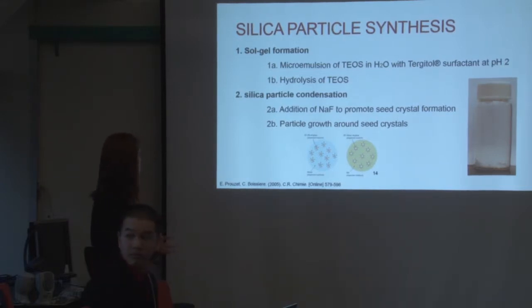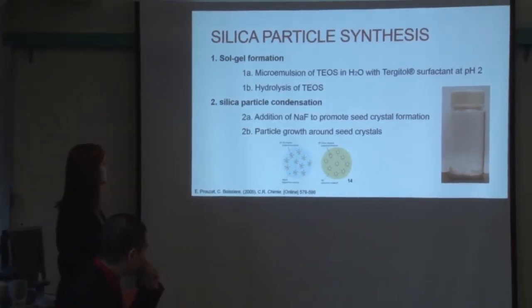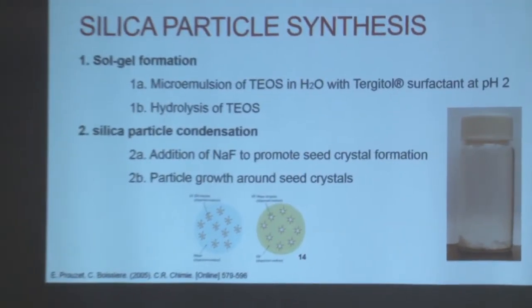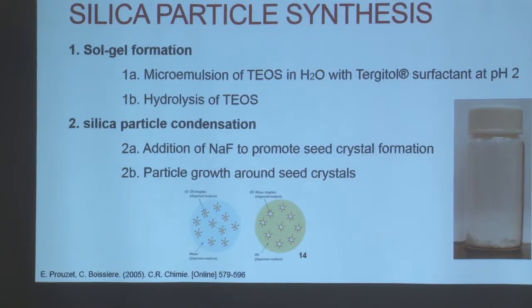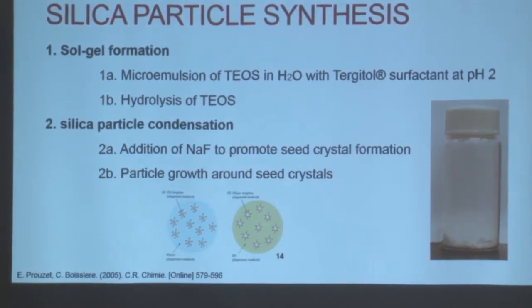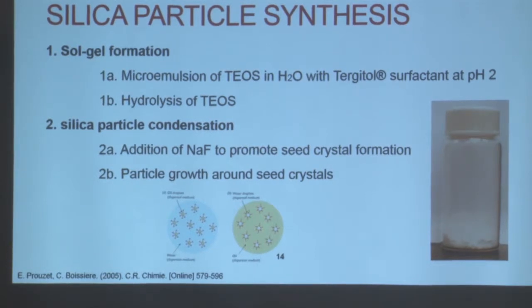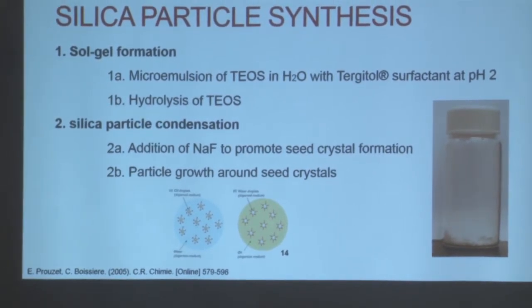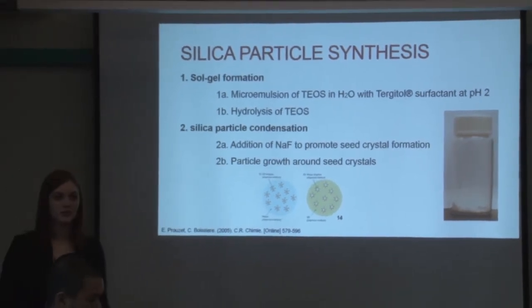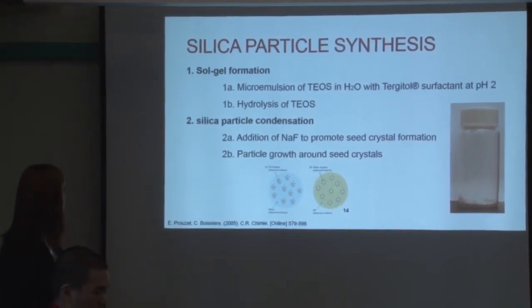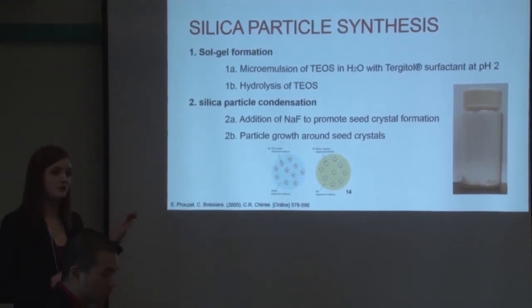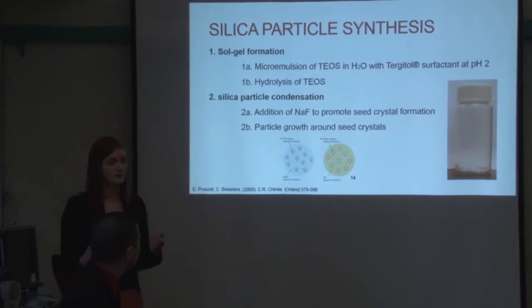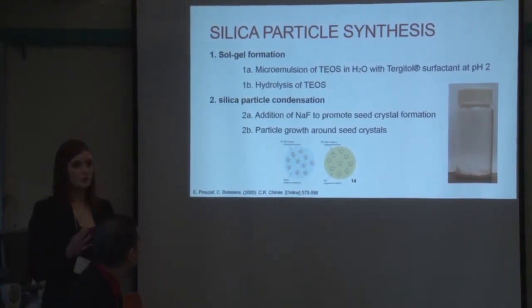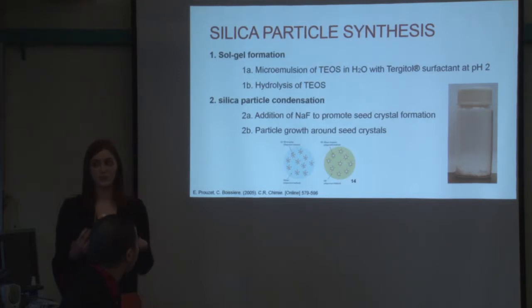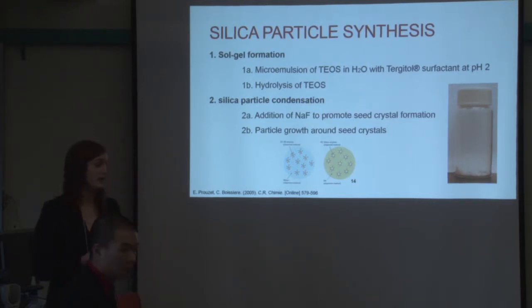So this is a procedural overview of some of the steps that we made to make our silica particles. It's basically a sol gel process, and it is done in an oil and water emulsion. We have the hydrolysis of our silica precursor, which is the TEOS, in water at pH 2 with a surfactant. Then we use a catalyst, which is sodium fluoride, to condensate our particles out of solution. This process is perfect for what we're trying to do because we have a lot of control over the different parameters of our particles. We could control the particle size by changing the ratio of silica precursor and catalyst, and we could also control the pore size by changing the amount of surfactant that we added.